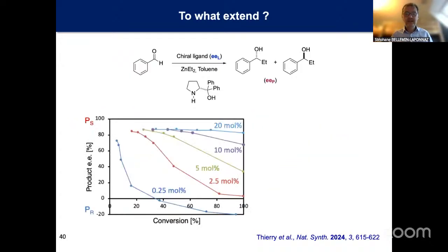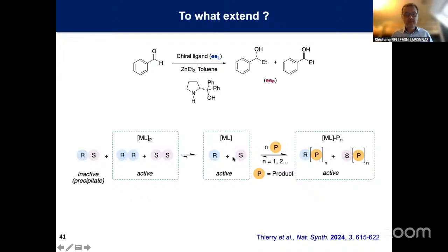What is even more surprising here is that the reaction is changing during the course of the conversion. So what you have here is the enantiomer selectivity as a function of the conversion of the reaction. If you have a lot of ligand, like 20%, the enantiomer selectivity remains the same. But if you have a lower amount of catalyst, you start from a high enantiomeric excess, and as soon as you generate the product, you generate a new active species that induces an enantiomer divergence. So what you have here is a competition between a first species that then reacts with the product to generate a new catalytic species that is inducing enantiomer divergence. And this is, for example, what we call the Soai reaction. The Soai reaction is a kind of auto-induced catalytic reaction.